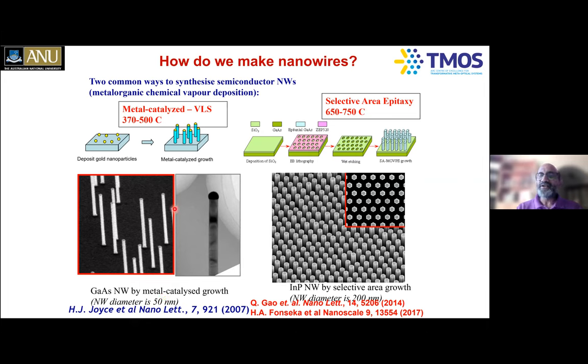And we were able to demonstrate these atomically perfect nanowires. And so then the alternative technique is called selective epitaxy. In this case, we don't use any metals because sometimes you don't want to use metals. For example, if you want to grow nanowires on silicon, gold and silicon don't get along well because gold acts like a non-radiative recombination center.